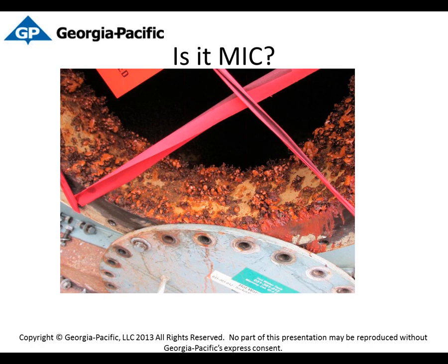We'd say, plate something out for us and test it for MIC. And they would plate, and they'd come back and say, you don't have any bacteria in your water. Your chlorine residual is good. And I said, well, I've got holes in my pipe and tubercles on my walls, so there's something in there. But they kept on saying over and over again, you don't have anything. And what we found through this whole process, and Dora is the expert on this, is that something like 90+% of bacteria we can't actually plate and grow. We actually just have to do a DNA test to see if it's there, because you can't get the environment exactly right.